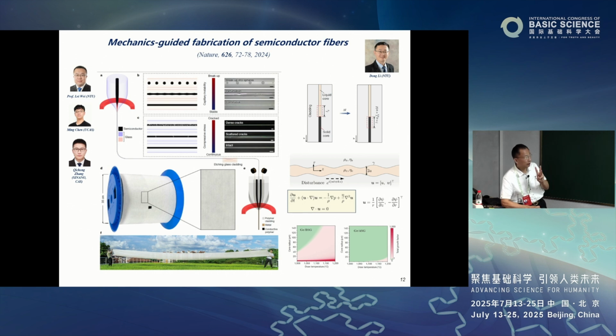But you have two challenges in this process. One is in the fluid stage, you have instability, a fluid-like instability, the so-called Plateau-Rayleigh type of instability. It's just like a water drop. You open a water fountain, and this water can break up into droplets. Same kind of instability. When you do the thermal drawing, this fluid state can break up into droplets, like the experiment shows. Another challenge is when you cool down into solid form, you can have cracks. You see here two examples with very dense cracks. Either when fluid instability or fracture happens, you cannot have long wires. Maybe you have very small pieces.